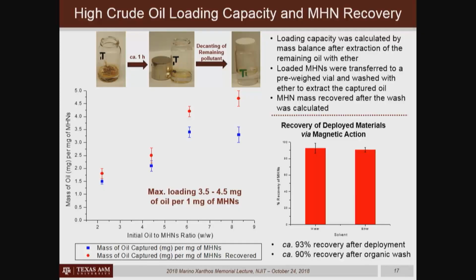But what Jenny further did was she confirmed that she could recover the material by the magnetic effect. Because if there are organic particles coupled to organic particles, we were concerned that they may not have an inorganic particle connected to them, then they wouldn't be collected when the magnet is used. And so what she found is that she could, in fact, recover about 90 to 93% of the particles. So 93% after deployment, and then 90% after organic wash to extract the crude oil out of the particles to allow them to be recycled.